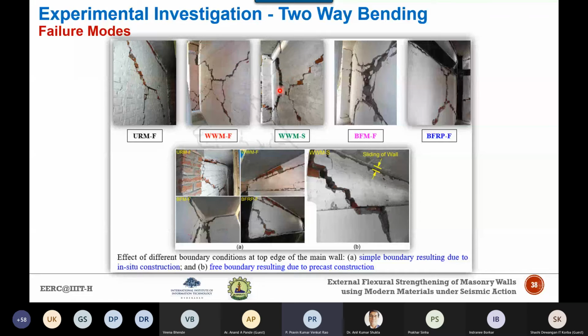However, in case of welded wire mesh with the flexible diaphragm condition, a vertical crack has been propagated through the bandage and the reinforcement, showing a clear picture. So in this particular condition, the wall has been distinctly divided into two different zones, zone 1 at the top and zone 2 at the bottom, when you have provided the rigid diaphragm condition. But in case of the flexible diaphragm, it has behaved totally differently, where there is no strength enhancement. I will show you through the bar chart, through the graphs, that the strength enhancement in case of the flexible diaphragm is very less, even similar to that of the unreinforced masonry, because in case of the flexible diaphragm, as I said, there is a lack of anchorage connection.